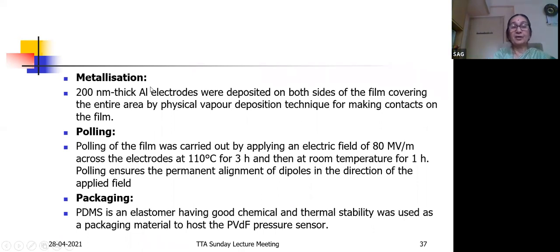and it requires a license to do anything with gold, because if you want to etch it, then the aqua regia, which is used for etching the gold, is very toxic, and you require a clean room. All the rules are to be observed, etc. So an alternative was aluminum electrode, which was deposited on both sides, 200 nanometer thick.